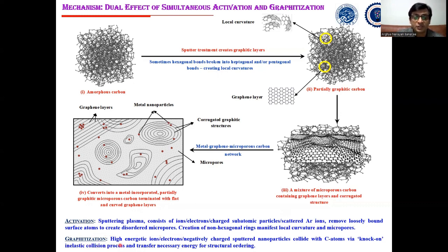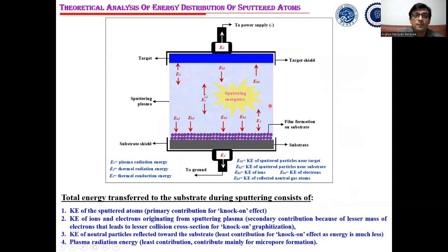On the other hand, graphitization is done by the high energetic ions, electrons, or negatively charged sputtered particles, which collide with the carbon atoms via knock-on elastic collision process or knock-on graphitization process to transfer necessary energy for this structural ordering or graphitization. Now, we also did the theoretical analysis of this sputtering system or the sputtering plasma to observe whether these sputtering particles have enough energy for activation or graphitization.